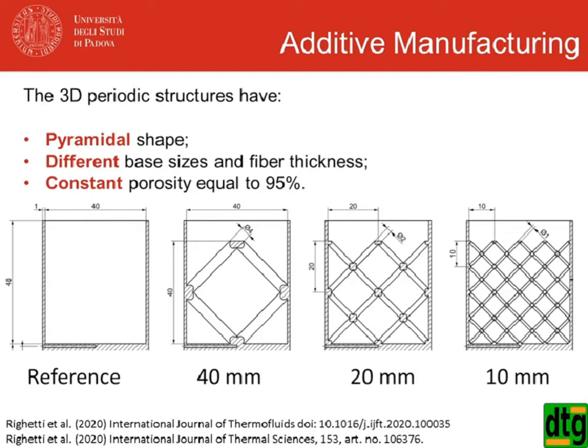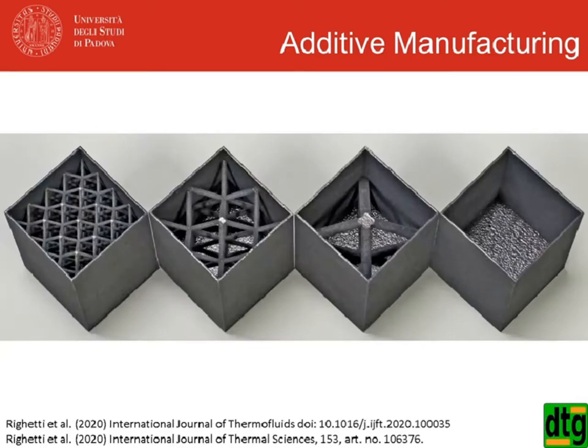What does it mean? It means that with foams we studied pore size up to around 5.5 millimeter, and now we want to move to bigger pores to see if there is a maximum pore size. Afterwards, we have a decrease in the performance of the system, because this phenomenon has to occur: while increasing the pore size, we can reach the limit of infinite pore size, which means an empty structure. Here you have just a photo of the samples, okay: the empty box, the 40 millimeter pores, the 20 millimeter pores, and the 10 millimeter pores.